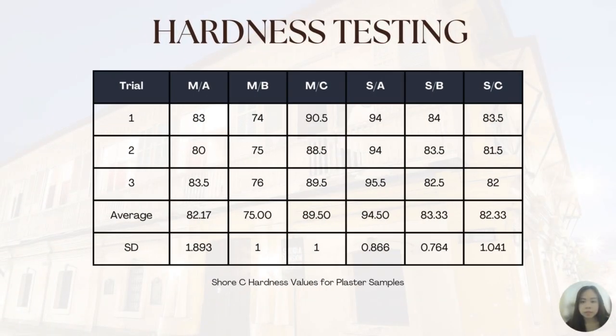adhesion. The Shore hardness test measured six plaster mixes under misted and submerged conditions. Submerged samples generally had higher hardness, with the 1:2 mix showing the highest average hardness. The 2:1 mix had the highest hardness among the misted samples. This suggests that higher lime content improves hardness in misted conditions, while a balanced lime sand mix is more effective for submerged conditions. The 1:2 submerged mix showed the most consistent results, highlighting its strength and stability.